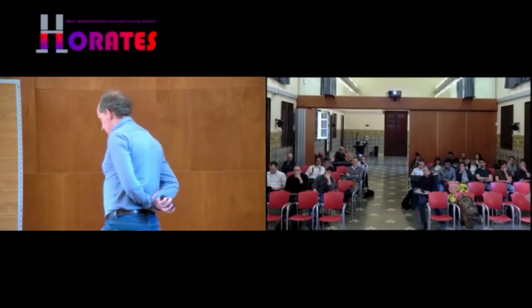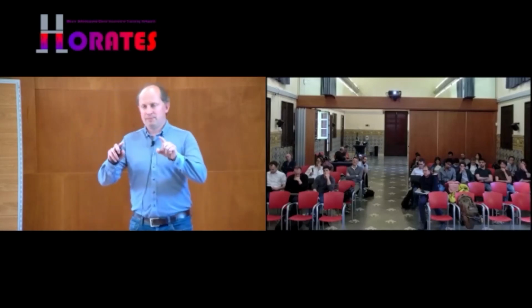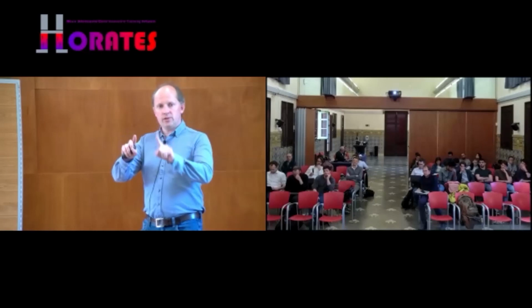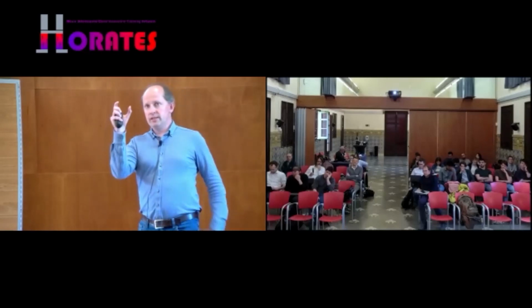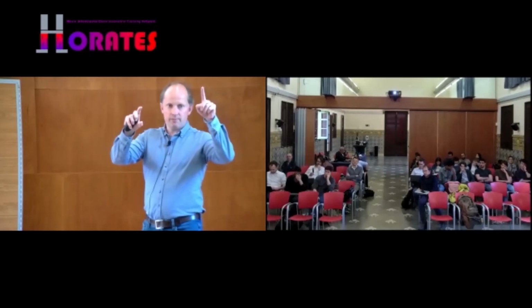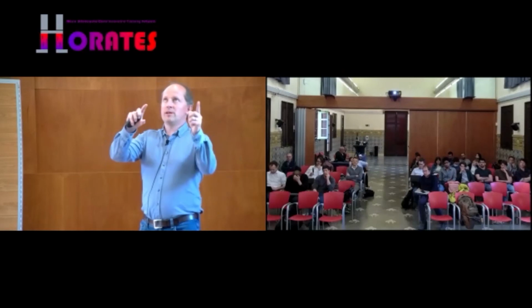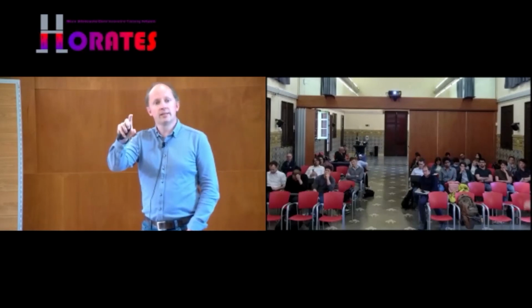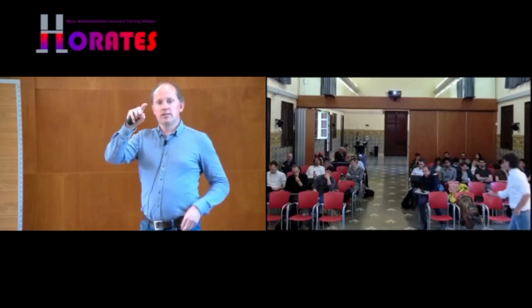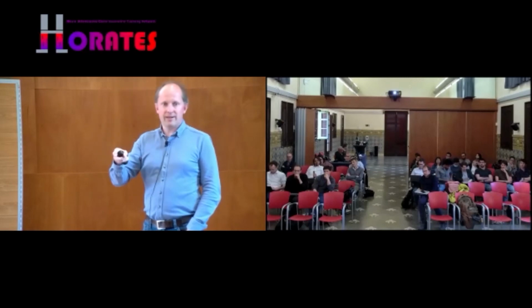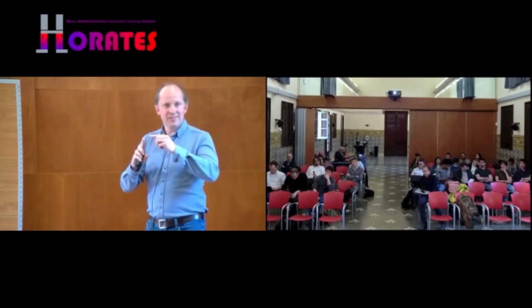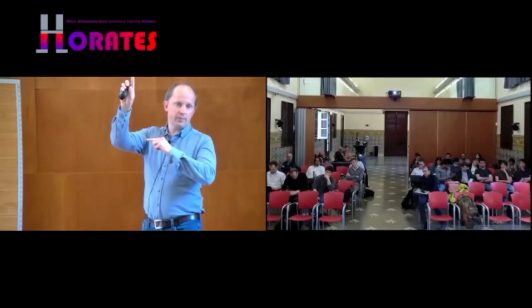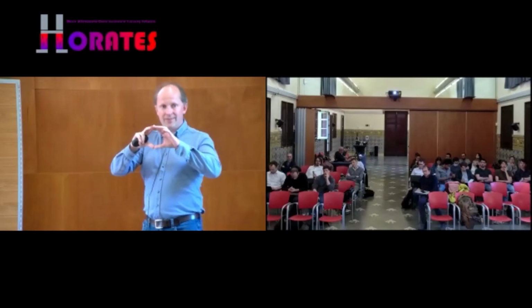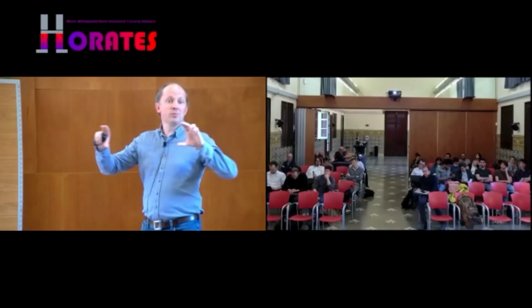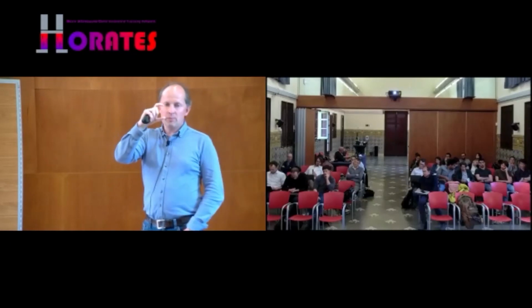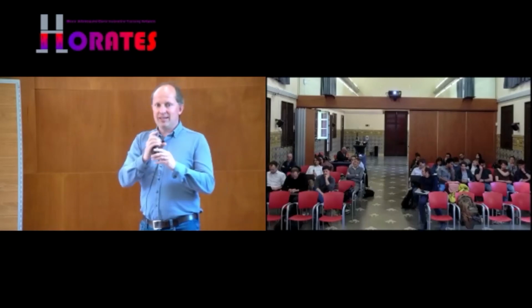Yeah. So I think there's a couple aspects to this. There were two things that we noticed as a function of temperature. One was the jump in thermal conductivity as you go down in temperature, or I suppose the drop as you go up in temperature, which seems to be linked actually to the lead iodide modes on that cage. So there's a collapse in the phonon group velocity along one particular axis. In the thinnest thin films, that axis points out of plane, so we don't pick it up. In the thicker film, there's a mixed orientation of crystallites, so we pick it up a little bit. That's what we believe is the reason for that change. So that's related to the lead iodide, not the methylammonium.